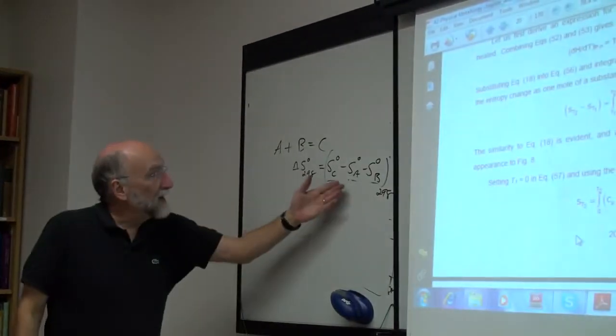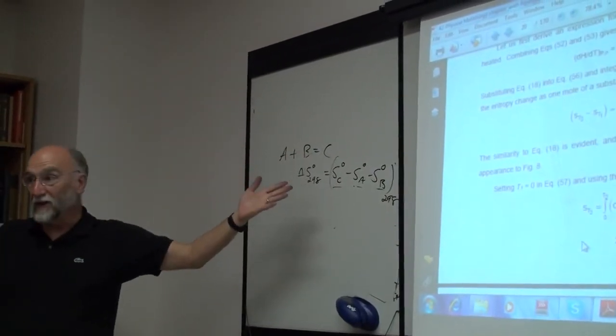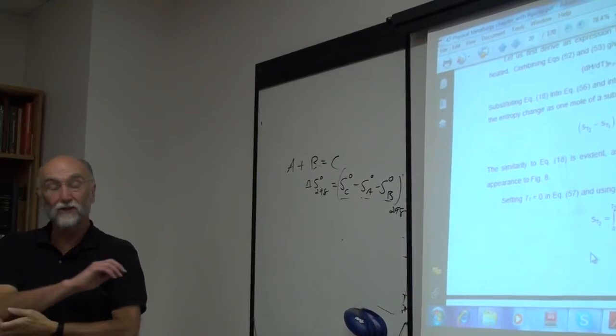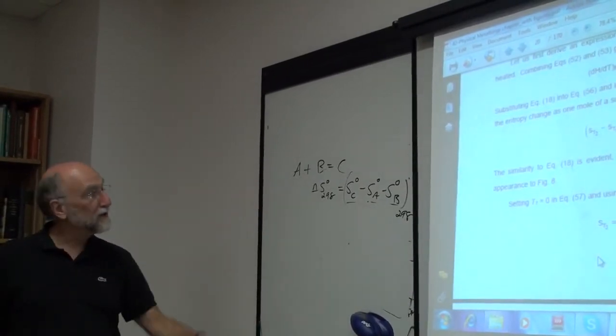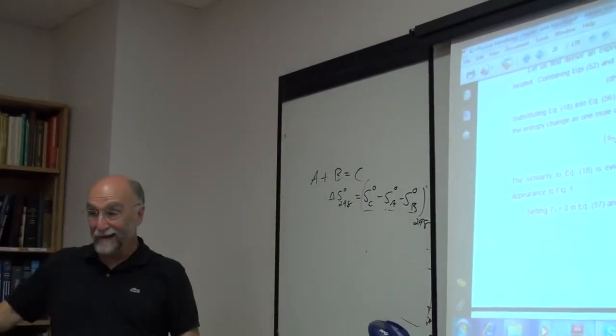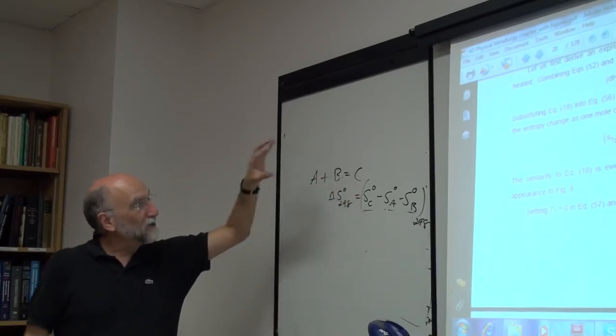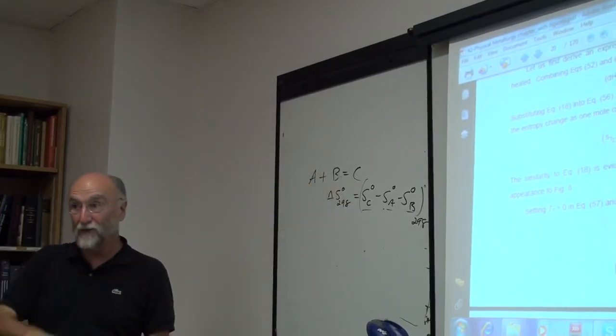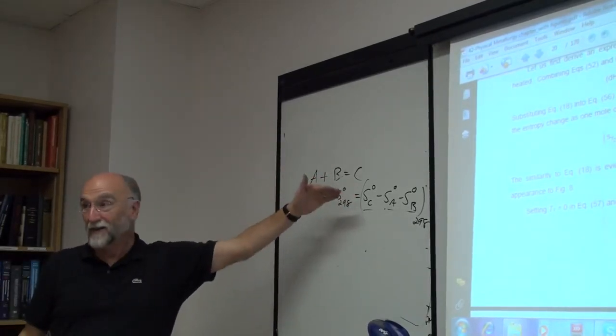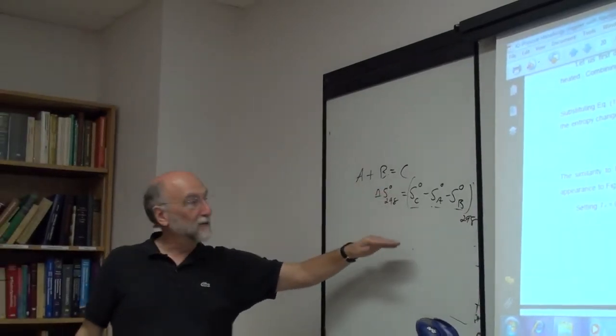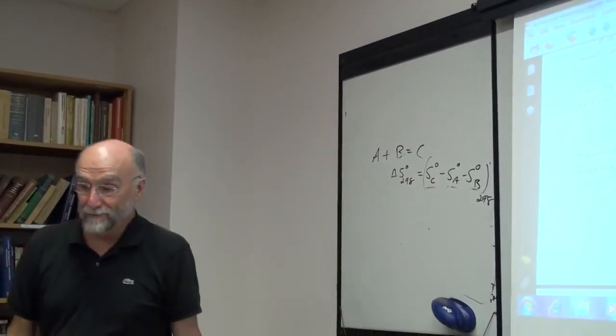Because you can't do this with enthalpy. I can't measure the heat capacity of a material between 0 Kelvin and T to obtain the absolute enthalpy, put them together and get delta H. You can't do it. If you want to measure the enthalpy, you either have to carry out the reaction, or you have to establish an equilibrium and measure it as a function of temperature, but you have to put the stuff together somehow. With the entropy you don't have to. Difference.